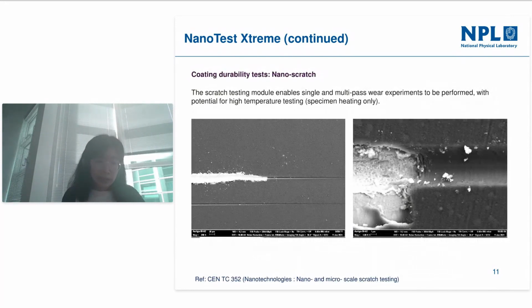So the next technique is the nano scratch. With the pendulum design, the scratch test module enables single and multiple pass wear experiments to be performed, and with potential for high temperature tests without indenter heating. The image on the left shows a single and multiple ramp load test, and the wear and the damage of the coating on a tool steel substrate can be seen from the images on the right after multi scratch pass of 100.